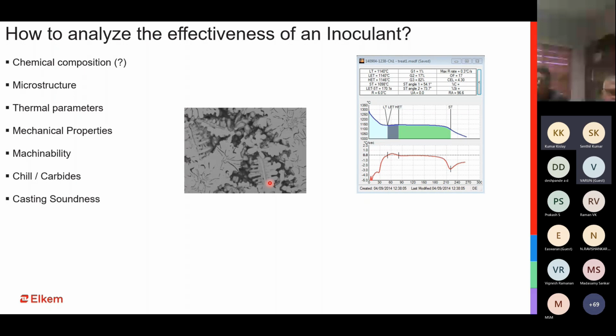And if the inoculation is so poor that you don't even see the graphite precipitating out, what you will see are these voids. These voids are basically shrinkage cavities, and these dendrites have made sure that any possibility of feeding liquid metal into these last-to-solidify sections has not been possible, and that is why this kind of shrinkage was faced by the casting manufacturer or the casting producer.